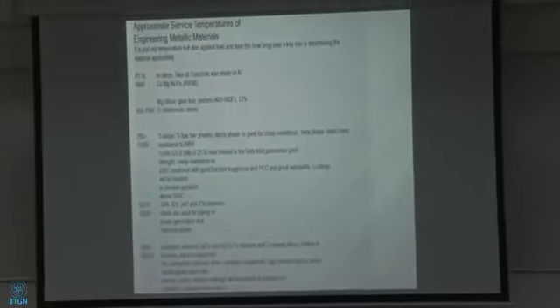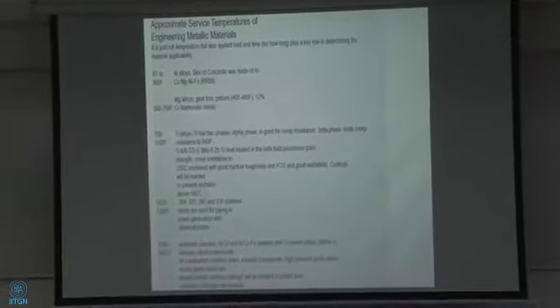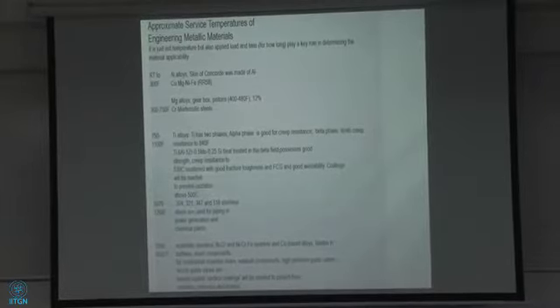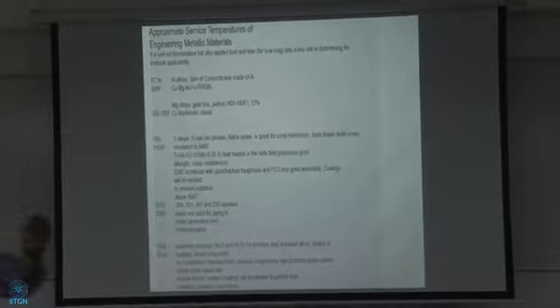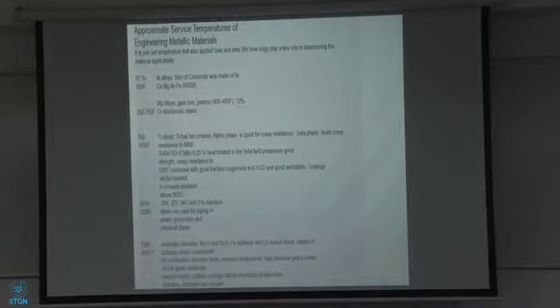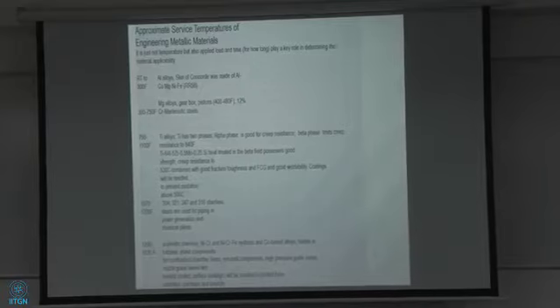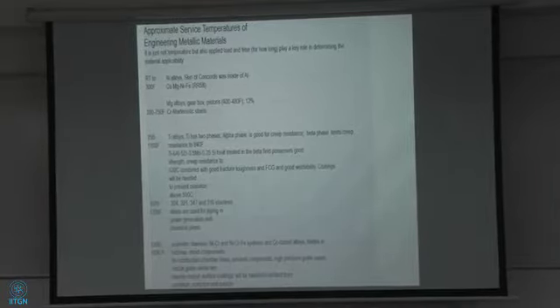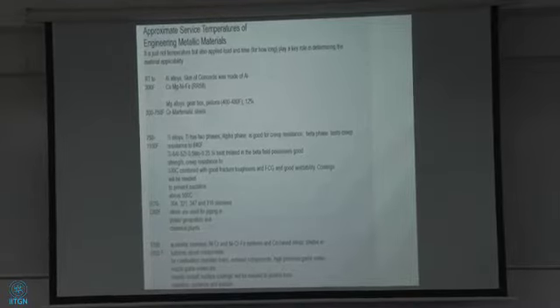So aluminum alloys, you can go up to 300 degrees F. But one thing I put here, you always have to ask not just what temperature you're going to operate at, but how long you are going to operate and what is the load. That's the important thing. I can always use any material for n number of hours, but if there's no load, there's no problem. If there's no time limit, then it's no problem. But once I put the constraints, I want to use it for 1,000 hours, under this load, then things completely change. The whole picture changes, right? So that's aluminum alloys.